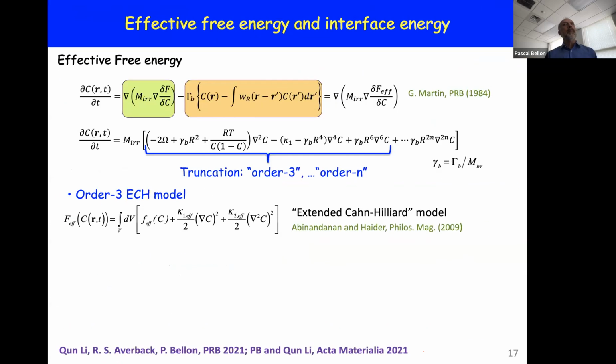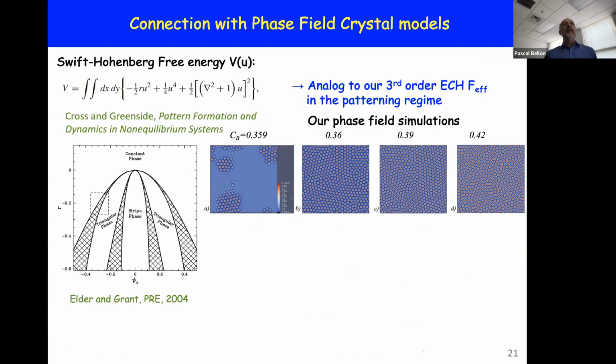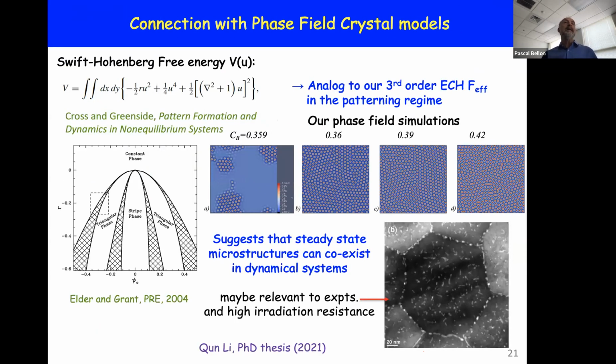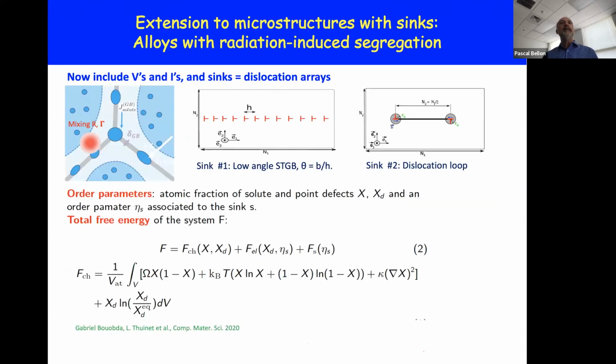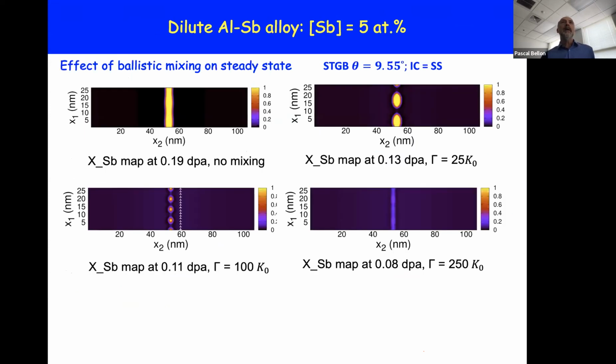Yeah, so some of the results I showed here were from that phase field crystal model you're referencing. We were surprised that the effective free energy function we derived for a system under radiation had the same functional form in the patterning regime as the Swift-Hohenberg one, or very similar, in some cases with additional modes. Here it's the case where we included grain boundaries. It's not obvious because this is a chemical map and we don't show the microstructure, but this elongated box is a system where there is a symmetric tilt grain boundary that runs along the vertical axis in the middle of the sample.